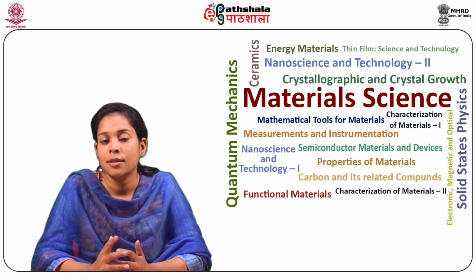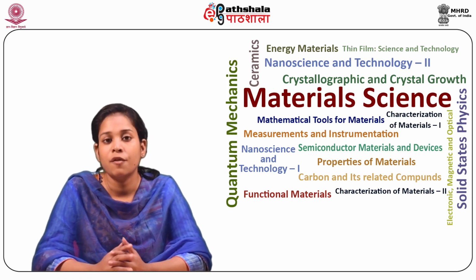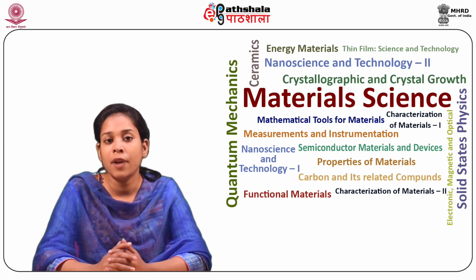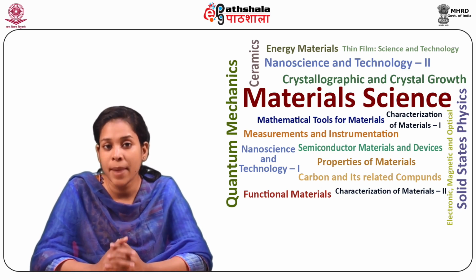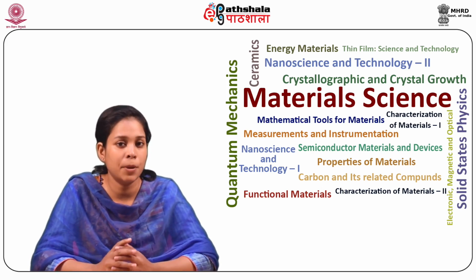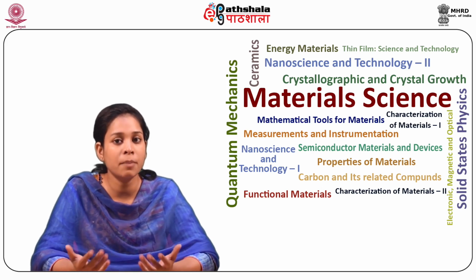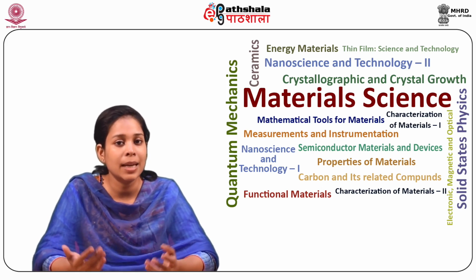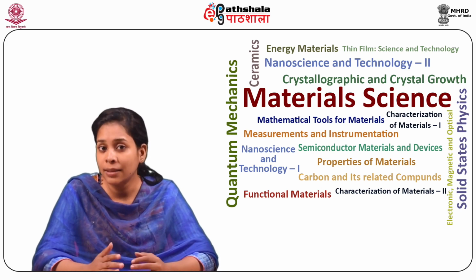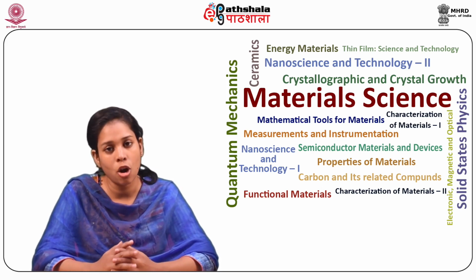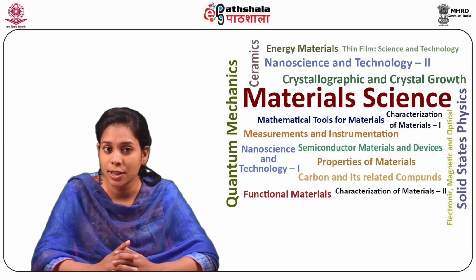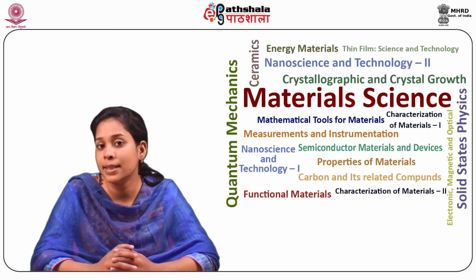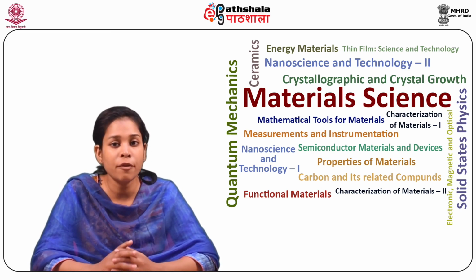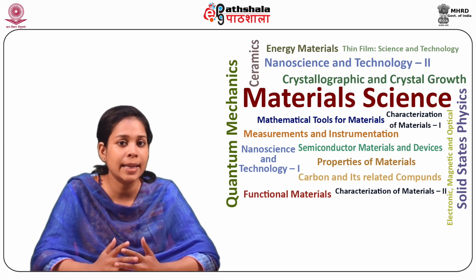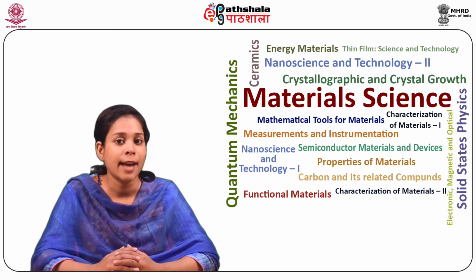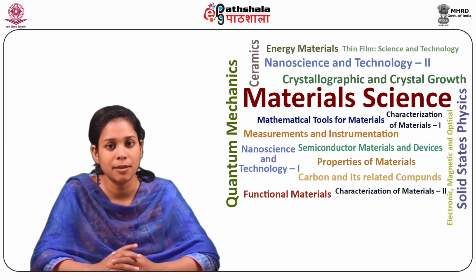So there are some other criteria for glass formation. One of these is Smekal's. Smekal proposed that for glass formation, the bonding in the material should be neither fully ionic nor fully covalent, but of mixed nature. The covalent bonds are highly directional and have rigid bond angles.